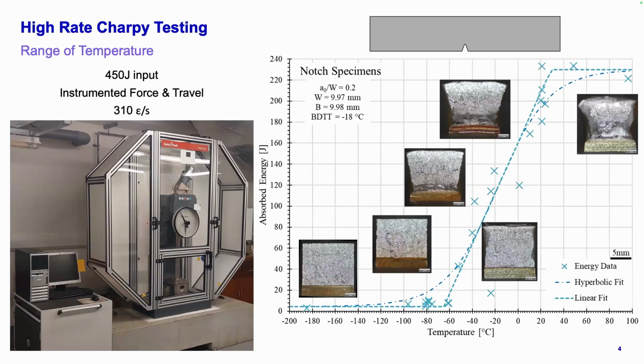coming to a good transition where we've got the fracture surfaces I've shown as well. These are for the notched samples, so the whole fracture surface went in one go after the notch. We have very classically brittle behavior transitioning to a very classical ductile behavior. Lovely. So that's the notch, that's the low constraint.